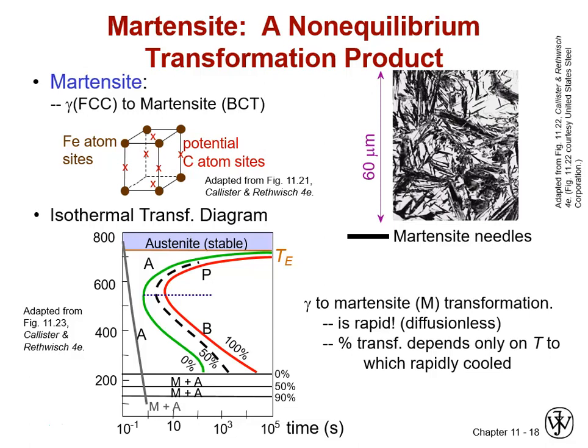It will kind of end up stuck halfway between a face-centered cubic and a body-centered cubic, an arrangement called a body-centered tetragonal, which is basically a body-centered cubic that's extended upwards to the point where it has a C-axis instead of just an A-axis. It's not a cubic anymore. It's got a longer axis in the Z direction, and with too much carbon in interstitial positions, octahedral and to a lesser extent tetrahedral holes.